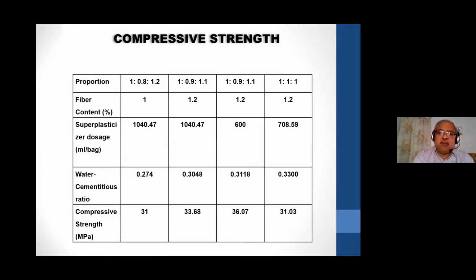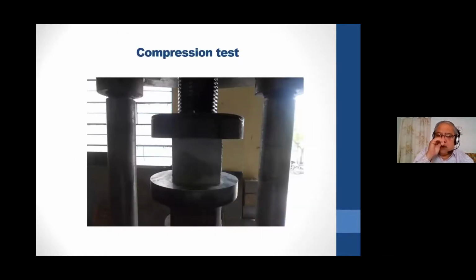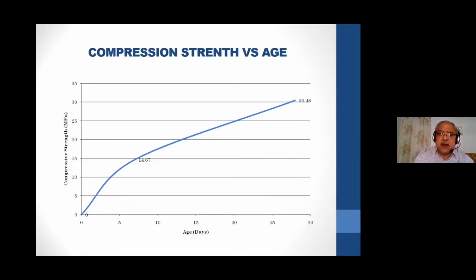These are the compressive strength results for the various proportions that we carried out. We changed the water cement ratio, superplasticizer dosages and fiber reinforcement. After all these combinations, we tested the fiber concrete, and this was the compressive strength with age.